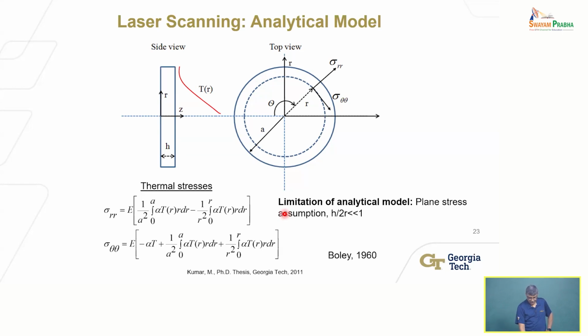So we did that. You can actually compute the radial stresses as a function of temperature and coefficient of thermal expansion, alpha, and you can do the same thing for circumferential stresses as well, right? So depending on where the tensile stresses are generated, they could be generated in the hoop direction or circumferential direction, or the radial direction.